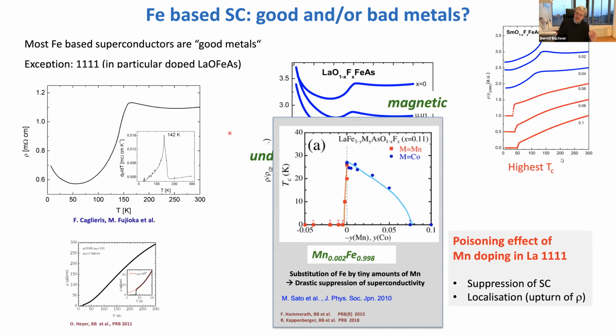Let me highlight another point. What's also quite characteristic for these 1111 type systems is something which people call the poisoning effect of superconductivity. So you start from an optimally doped lanthanum 1111 type system, you plug in 0.2%, that's basically nothing, of manganese, and you destroy superconductivity. And it's not only superconductivity which you destroy, you can have a closer look at these publications. It's a normal state which drastically reacts to tiny amounts of disorder. Again, telling you that these systems are far away from being easy, simple, good metals.